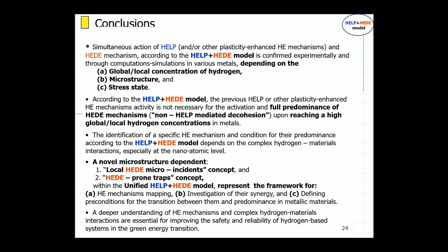We propose non-HELP-mediated decohesion, which is totally opposite to the HELP-mediated model by Robertson and Sofronis. Also, we introduced two new concepts: the local HE micro-incident concept, still in development, and the HE-prone concept as a part of the unified HELP plus HEDE model. The framework is hydrogen mechanism mapping, investigation of their synergy, future work, defining preconditions for transition between them, and predominance in metallic material of these two groups of hydrogen embrittlement mechanism.